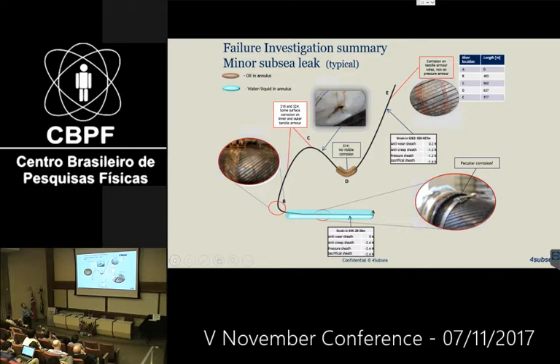Then what we often find is that this region of the riser is more or less restricted from the flow. So if you remember, I showed the graph where I showed that the free annulus volume is often reduced with time for production risers. That is related to something accumulating down here. So we have seen that after some years of operation of very many production risers, not equally much on gas risers, this area here is restricted. So we will then very often find a situation where we only measure free volume here. Then you have an area here. It might be filled with water, it might be empty, or it might be something else.